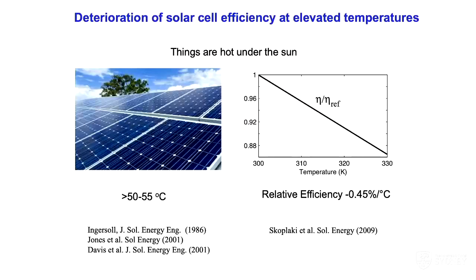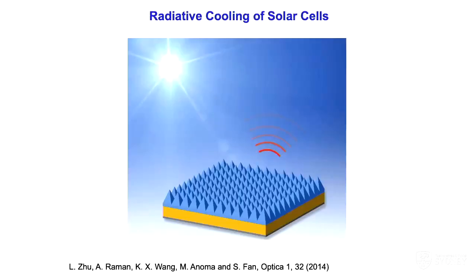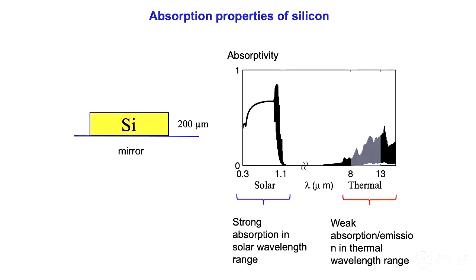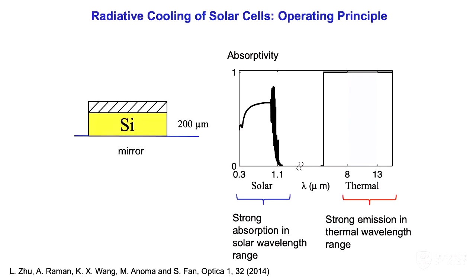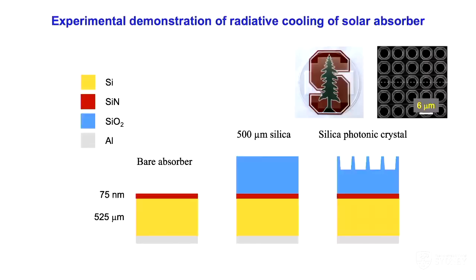The solar cell certainly faces the sky, so it will be interesting to combine solar cell technology with radiative cooling. Here is one illustration of the idea. If you take a piece of silicon, it absorbs very strongly in the solar wavelength range, and this is how you build a solar cell in the first place. It turns out that silicon is not a very strong thermal radiator due to its chemical structure. So one thing you can do is try to enhance the emissivity of silicon. For example, you would like to put something on top of the silicon absorber that is visibly transparent so that the sunlight can go through. But in the infrared, you want to enhance the emissivity so that you can radiatively cool the silicon cell underneath it. And we illustrate this idea with an experiment about a solar absorber.